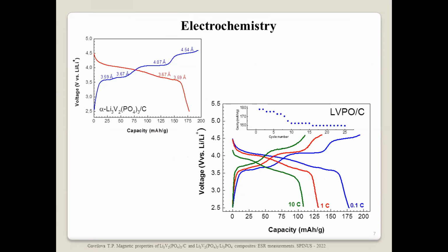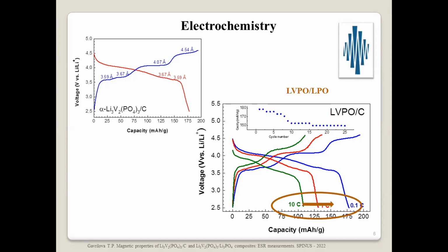Unfortunately, experiments for the other composite are not finished yet because we have some troubles, not with the sample, but with equipment. At this moment, I'm glad to say that we have already bought our own equipment, and now in Kazan Physical Technical Institute we can perform these experiments on electrochemical properties measurements. And at this moment I can say that for lithium vanadium phosphate with lithium phosphate we can observe the same value of electrical capacity, but this capacity didn't decrease with increasing charge rate. It means that this curve with high charge rate should be moved to the right. It's very important from a practical point of view.